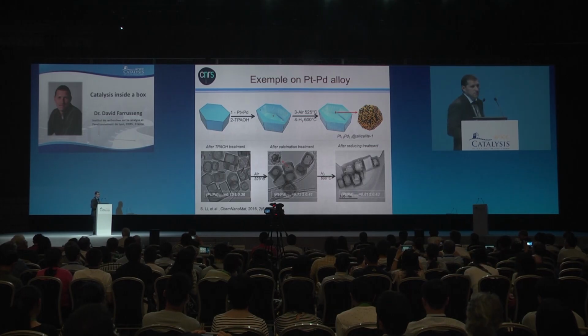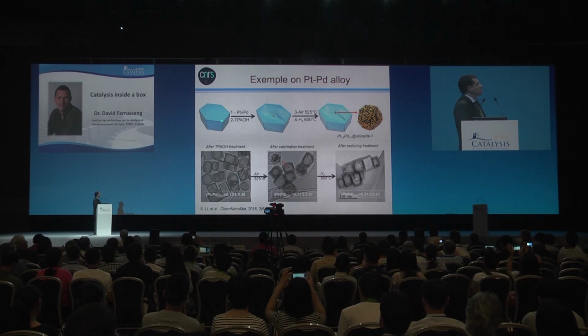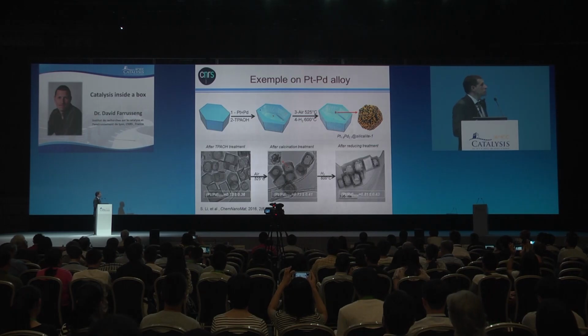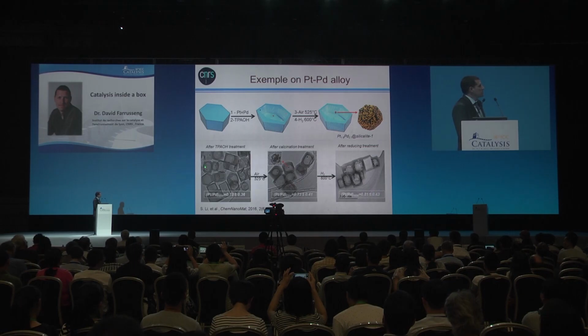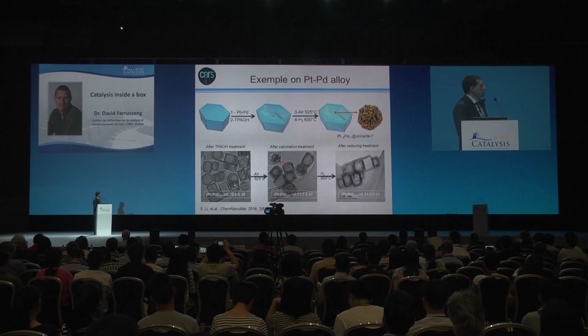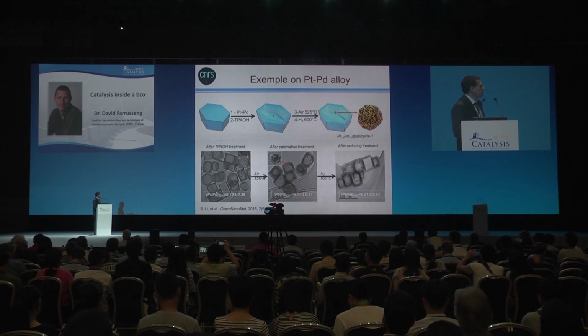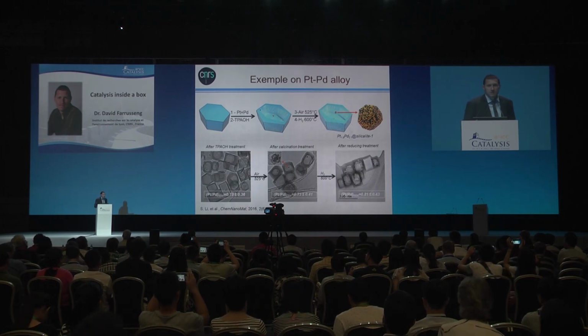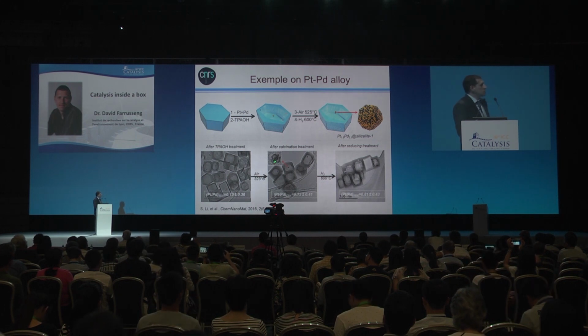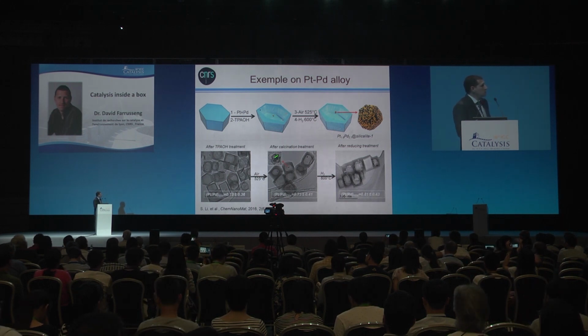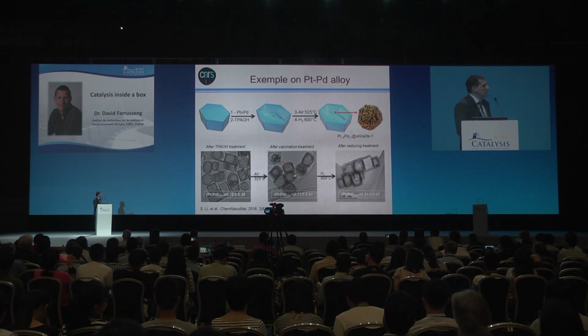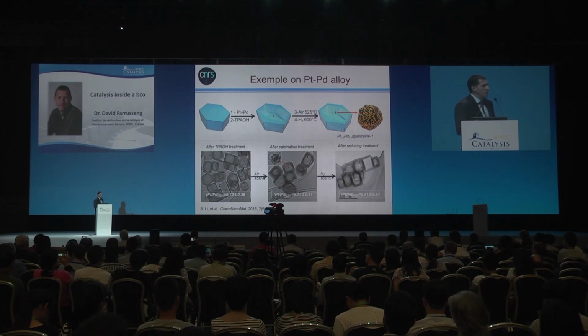So here are the results of that. We start with a single crystal. We do the impregnations of platinum and palladium solutions. And after the heat treatment, this is what you get. So a black deposit or black precipitate, which are the metals in every cavity, with a Pt-Pd ratio that corresponds to the expected amount. After calcination, you have more rounded particles, but still not perfectly rounded. It's only after the reducing treatment that you get a perfectly rounded nanoparticle that we believe is an alloy.